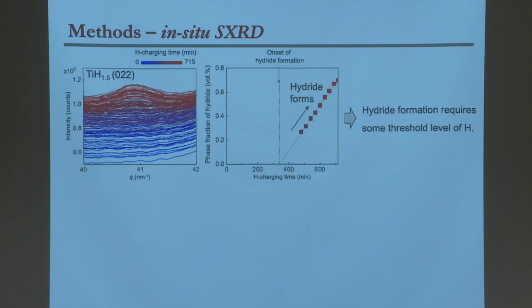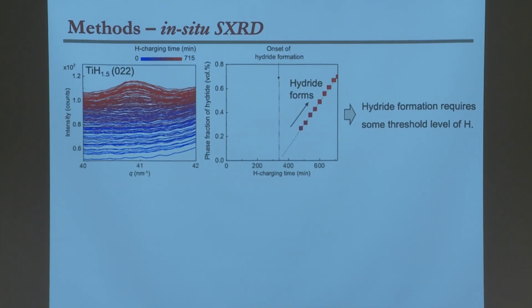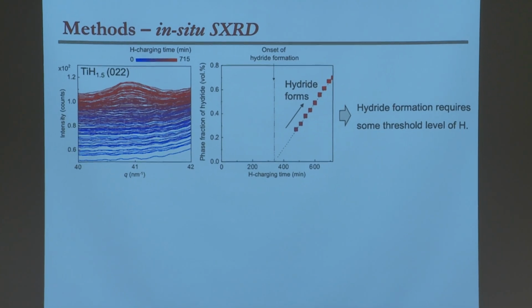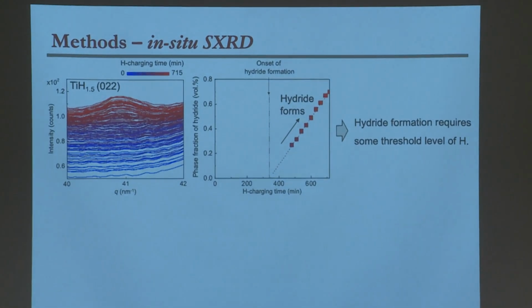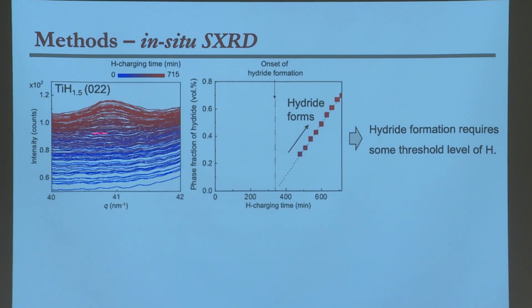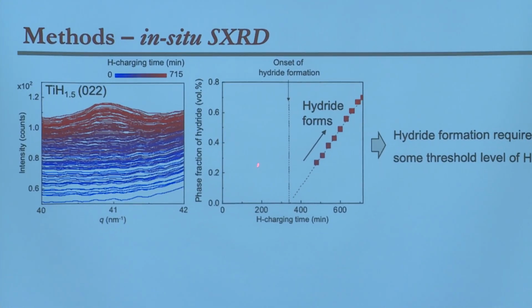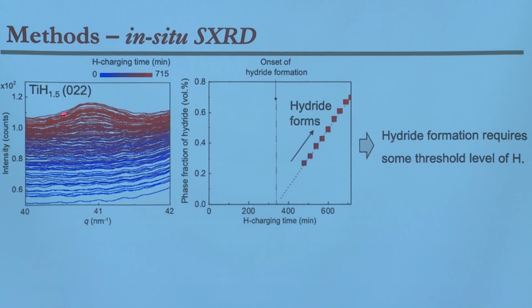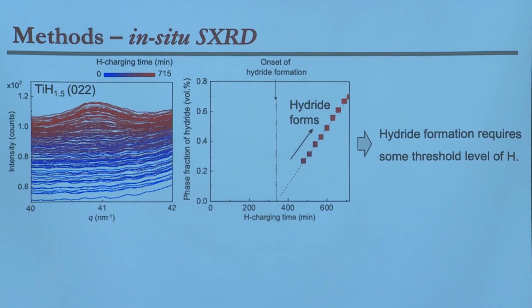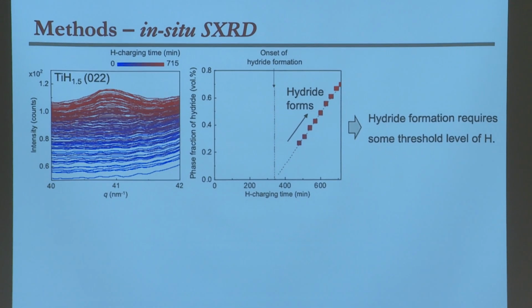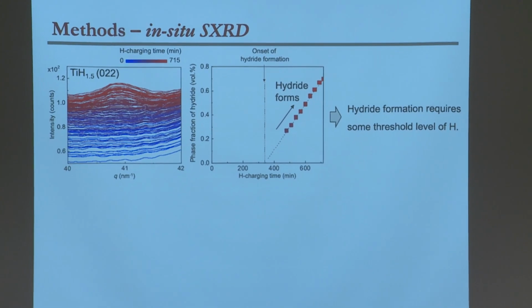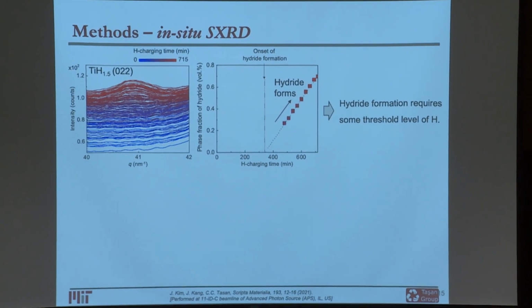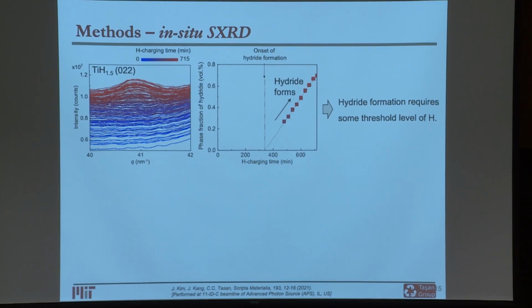Remember, we can't see hydrogen so easily, and we are trying to understand where it goes and what it causes, right? So in the synchrotron, we go to the synchrotron and charge a sample with hydrogen as we are having the synchrotron beam penetrate through the sample. We can, of course, do diffraction, and this can give us a lot of information. So some of this information is shown here. Here we are, for instance, looking at one of the hydride peaks that may appear in a titanium alloy when you charge hydrogen to it. So titanium is a hydride former, so if it takes hydrogen, it starts forming hydrides. But it's important to know when they form and where they form and so forth.